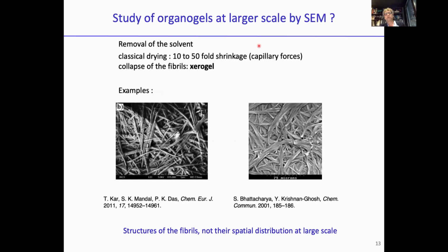Now, what we wanted to know is also what the distribution is at larger scale. Because on TEM, we work on a narrow field. What happens if we have large fields? This is why some others have tried to remove the solvent and observe the resulting object by a scanning electron microscope. And if you do so by classical drying, you will just dry the gel, and because of the capillary forces, you will shrink and collapse the structure of the gels.